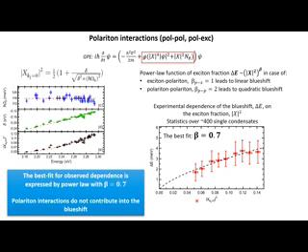This is a very important dependence because it allows us to examine polariton interaction. We can see here that the modulus of X squared corresponds to exciton fraction, and beta equal to 1 corresponds to linear blueshift, so-called exciton-polariton interaction, and here a polariton-polariton term would result in a power of 2 in exciton fraction.